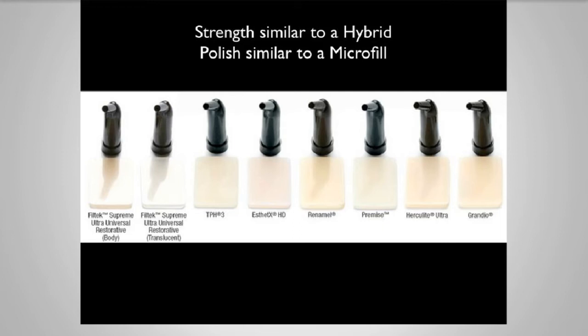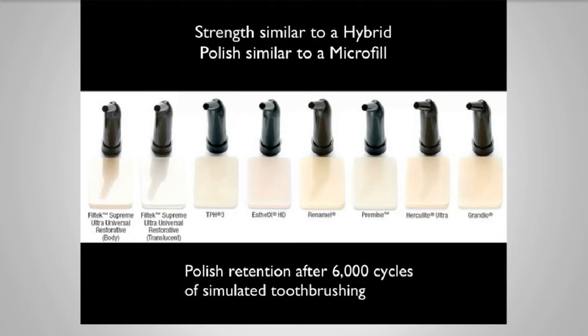So these tabs that are laying on this screen show you what some of these materials look like after about 6,000 cycles of simulated brushing. And this is after they've obviously been polished. The ones on the left are your nanocomposites, and then you have your hybrids. And the one that's closest is the microfill Renamel, which is a wonderful microfill that a lot of people use, and I still have in my practice. So nanocomposites give you that advantage of strength and polishability, which is really wonderful. And a number of companies are producing really nice nanocomposites. So that's what I'm using.